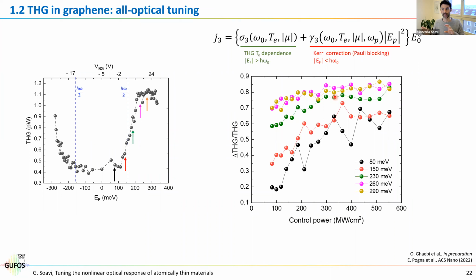And what is interesting is that Pauli blocking and electronic temperature have opposite behaviors in terms of positive or negative modulation of the third harmonic efficiency. So the fact that we always see a negative modulation of the third harmonic is because there is this combination between Pauli blocking and electronic temperature. So now we are trying to build, together with Habib Rostami, a theory that includes both effects. So this is the dependence on electronic temperature, what we discussed before, and this is now what we call a Kerr correction that includes the Pauli blocking. Okay, this work is ongoing. I hope I will be able to provide more details in the next few months.